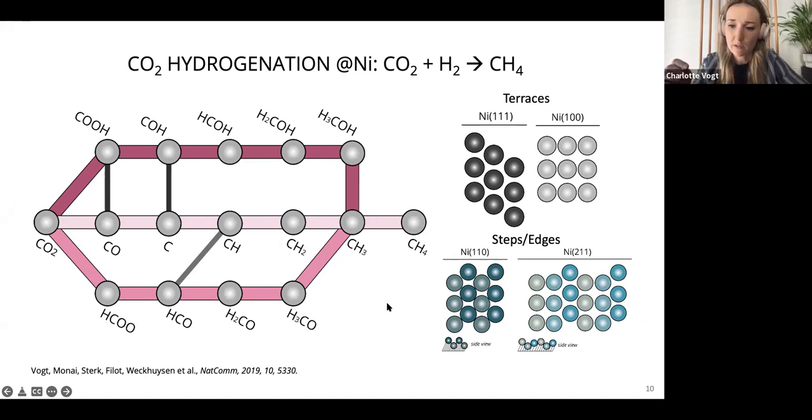And what we did here was we took these single crystal facets, right? This Langmuir approach, basically calculated the adsorption energies on all of these. From there, the activation energy barriers, etc. And we used the information that we obtained from these facets, superimposed, to build a nanoparticle, and thereby rationalize some of the things that we wanted to rationalize.